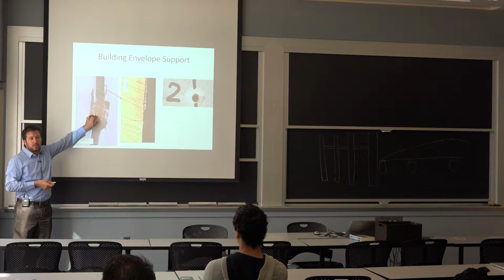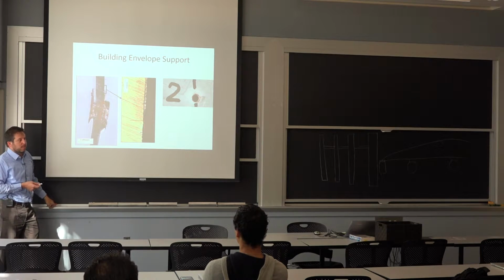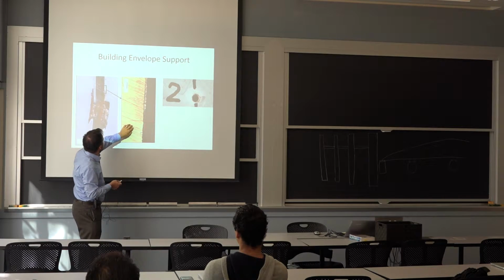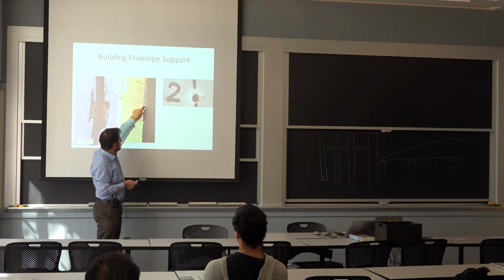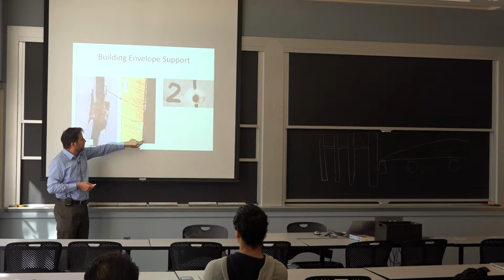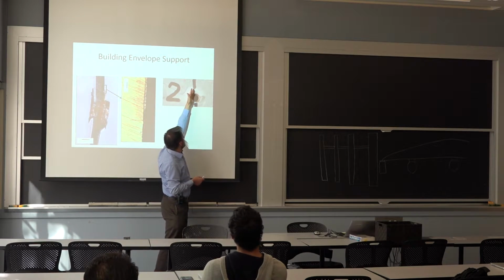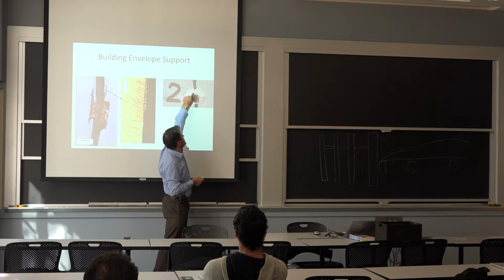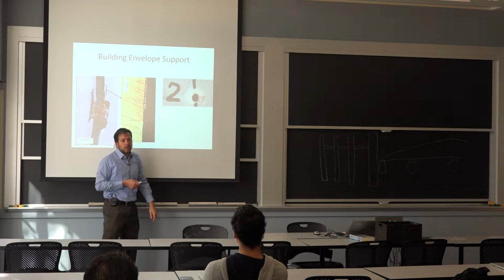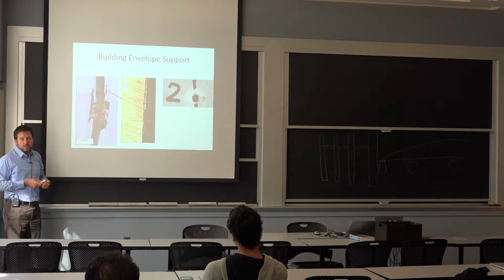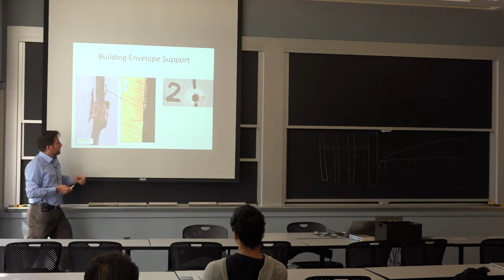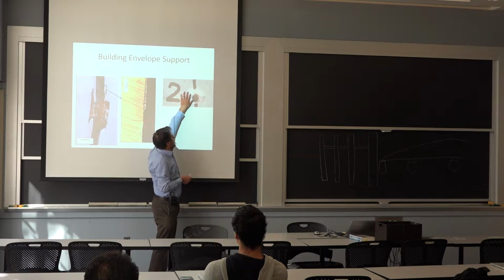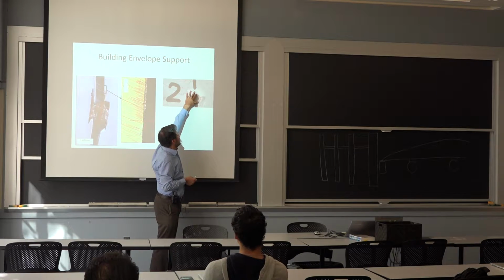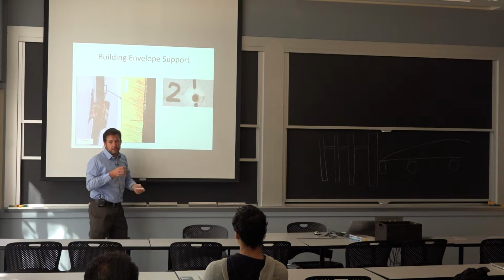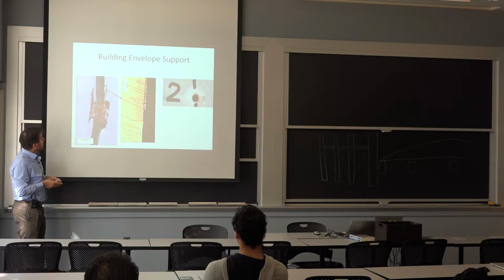So that will expose some fresh steel to the environment. And you can see on this micrograph, our 20 micrometers here goes to absolutely zero very next to the hole. So this view is a cut view of this region, and this distance is about 3 or 4 millimeters, where essentially you consume the entire amount of zinc. And then because the vapor or the condensation zone is only limited to a certain area, you're not using any of the other zinc that's out there. So it's a little bit of a detrimental effect.